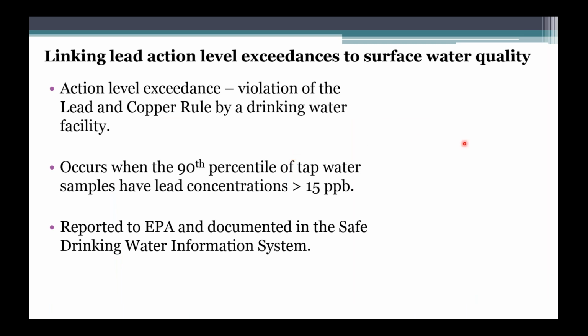Okay, so now I'll talk about one additional analysis included in this study. This one was looking at the linkages between surface water quality and the occurrence of a lead action level exceedance at a drinking water facility. An action level exceedance is a violation of the lead and copper rule by a drinking water facility. It's defined as a situation when the 90th percentile of tap water samples is above 15 parts per billion in lead concentration. In other words, more than 10% of the samples taken from tap water in a distribution system were above the 15 part per billion limit.